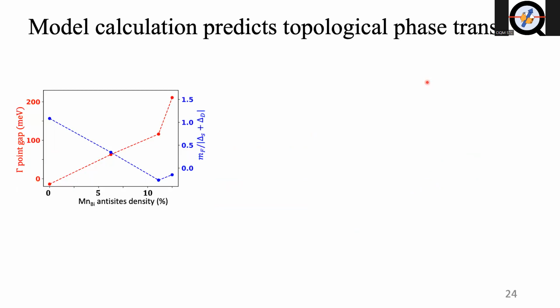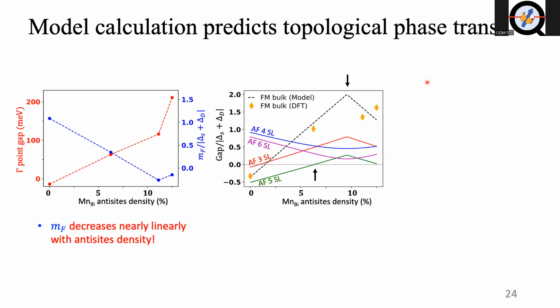We can see that as a function of manganese-bismuth anti-site density, the exchange coupling potential MF decreases nearly linearly. And how about the calculated gap? First of all, let's take a look at the ferromagnetic case. Our model calculation and DFT calculation agree pretty well. And then the thin film case, especially the antiferromagnetic five septuple layer case, which is of the highest interest to the field, because this is the film that people argue could show the quantum anomalous Hall effect. I can see that with increasing manganese-bismuth density, this inverted gap shrinks. Inverted gap means topological phase. And this inverted gap disappears at about 6%. And this signifies a topological phase transition at this point. So above this point, it's no longer a topological phase anymore.